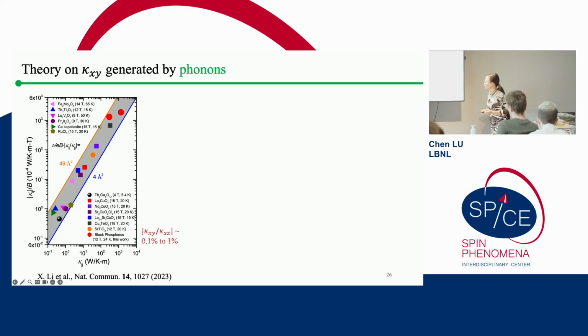And one striking finding is that in the majority of the materials in this table, for the signal coming from phonons, one value, the so-called thermal Hall angle, which is the ratio between thermal Hall conductivity and thermal conductivity, always lies within a certain range, which means it's below about 0.1% to 1%. Okay, so this is an empirical finding for these types of phonon thermal Hall effect in general.